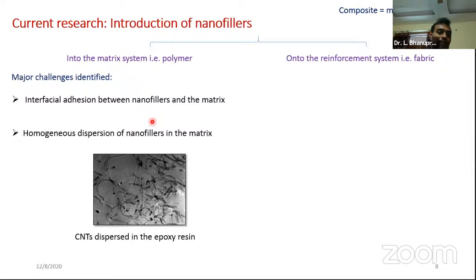Agglomeration is what we can straight away expect from nanofillers, because of their dimensionality they have very high surface energy. When high surface energy is there for any material, it tries to reduce it, right? That's why in the winter season we fold ourselves to reduce the surface area, so that we are less likely to be affected by the cold. In the same way, nanofillers try to reduce their surface energy by joining with adjacent material. So all the nanofillers come to one location and form an agglomeration. With such agglomerates you eventually lose the nano-dimensional properties, because the agglomerates come into micro scale, where you will not see any difference in properties. So the critical challenge is getting homogeneous dispersion.